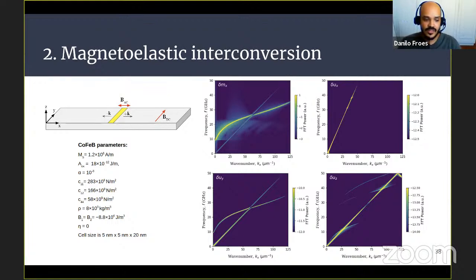By doing a two-dimensional fast Fourier transform, we can obtain the frequency and wave number dispersion relations. What's important to highlight here is the magnetic mode, this is the magnetic curve, and we have the linear elastic curve with the anti-crossing here, in the 25 gigahertz frequency region. We have two elastic modes, one in the x direction, the longitudinal one, which has a high slope. In the transverse directions, y and z, we have another slope, the transverse velocity, which is smaller compared to the longitudinal one, and only the transverse components hybridize with the magnetic one. We did not have this hybridization with the longitudinal one.